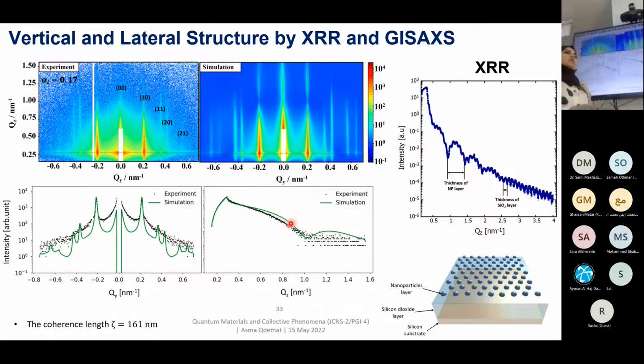That means we have a good estimate of the particle height, or the nanoparticle layer thickness. Also, from the horizontal cut, we can see some fluctuation or difference between the experimental and simulation data, which is due to the inhomogeneous orientation of the domains.